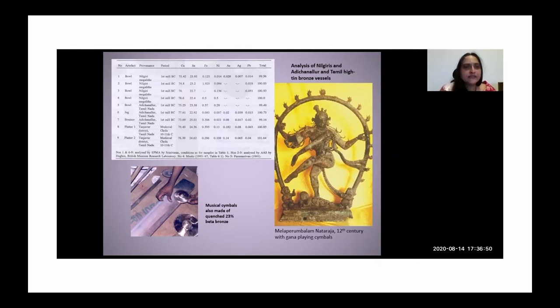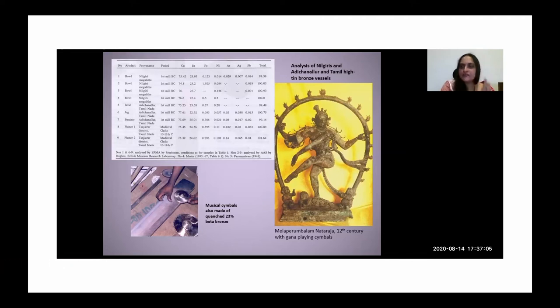These are from the Nilgiris and Adichanallur, and also some of the continuing ones that I was mentioning from the Chola period. And note here, the composition is all between 22 to 23%, 24%. They were all aiming for this beta phase compound, which has a composition of 23.9% tin actually. It's an intermetallic compound. And there are no traces of iron or nickel or arsenic, silver. And so they were really aiming for this kind of composition. And so that's just to ascertain that, so that you would see what I was saying.